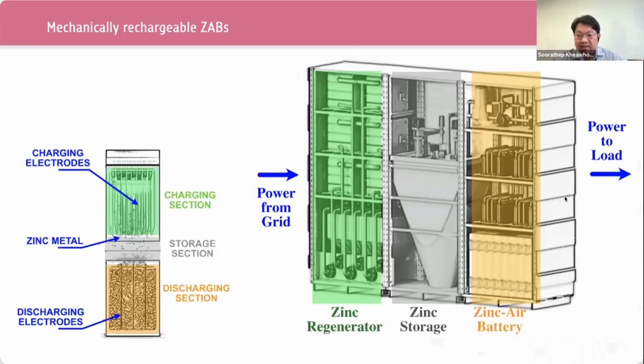The presence of dendritic particles in the distributed flow system has some advantages. First, dendritic shaped particles are more fluidizable and have better transport properties than compact bulkier particles, thus aiding the scaling up of the distributed system, providing a large range of flow rates while incurring lower energy loss for fluid transport. Second, dendritic particles are produced in a manner in which the attachment to the surface of the regenerator electrode is less robust than planar plated or densely formed particulate formations. Such a process benefits the removal of particles from the electrode surface since less energy is required.